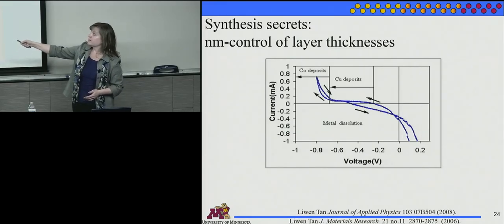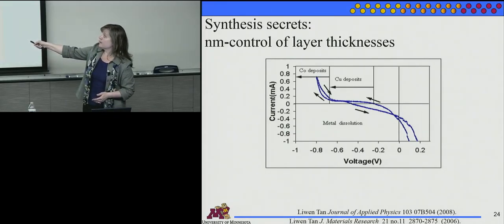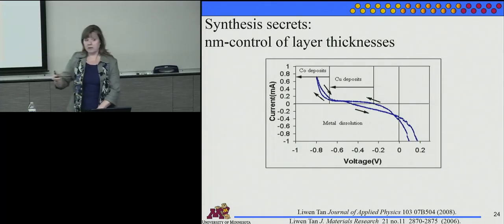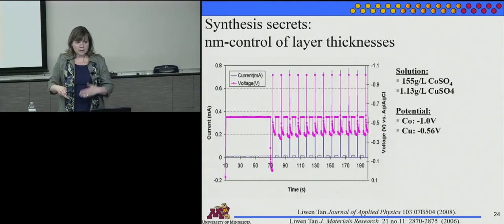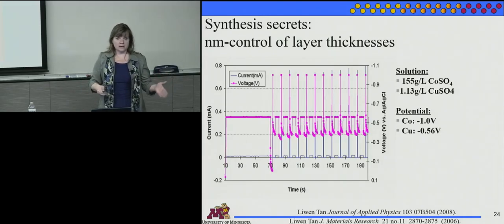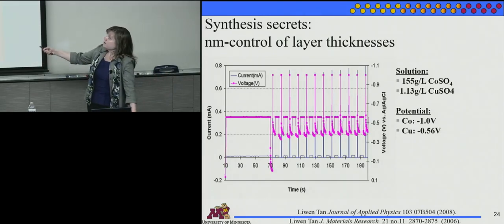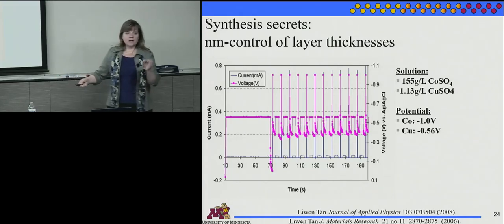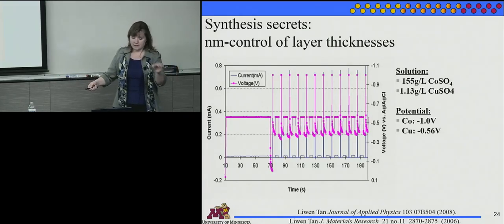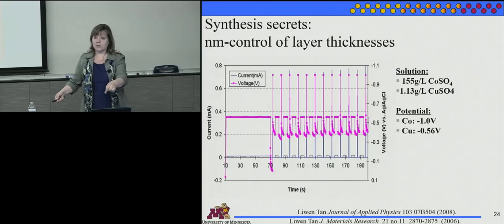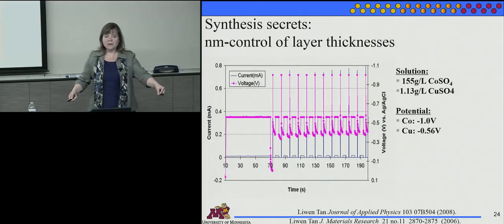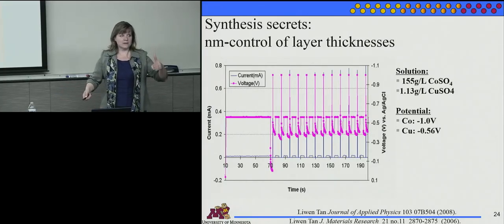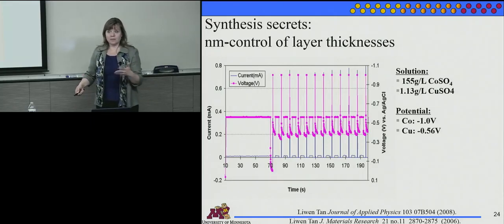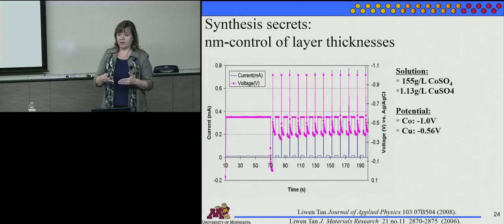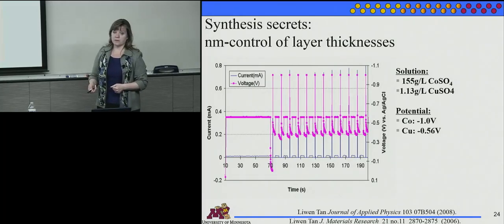And here we're depositing copper. We start depositing cobalt here. And then you etch the material if you're at a different voltage. So you just need to be aware of what's happening in the solution as you go. And so here's the trick of growing multilayers. Fine if you just want 3, like a reed sensor. Just put it in one electrolyte, switch to another electrolyte, switch back to the first one. But if you want to build up 300 layers, so you make good RAM-type devices or these barcode devices, it'd be nice to have all those layers grow in one solution. Leave it in there and just change the voltage.